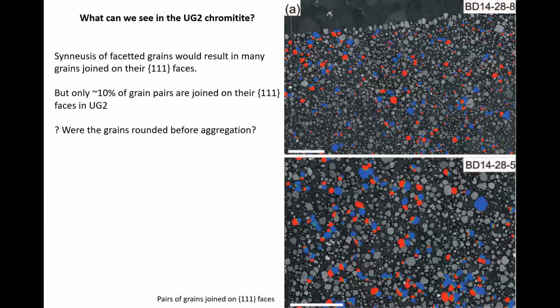So let's go back to the UG2. What can we see? Well, if these grains had formed those chains of beautiful faceted grains, like we see in rapidly cooled rocks that have just quickly erupted from a magma chamber, then we would expect to see many pairs of grains joined on their 111 faces, because those are the euhedral growth faces that we've got in a chromitite. But we don't. On this diagram, these are 2 separate samples, and we've got red and blue grains, and they're joined on their 111 faces. And you can see it's about 10% of the grain pairs are joined like this. So it's not the same as what we're seeing in lavas, the rapidly cooled rocks.